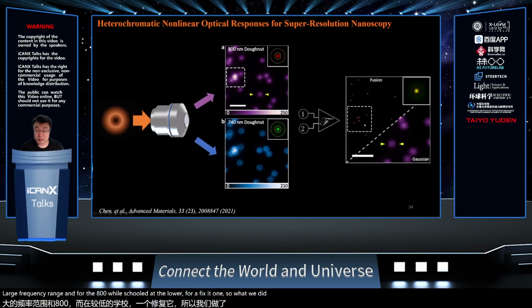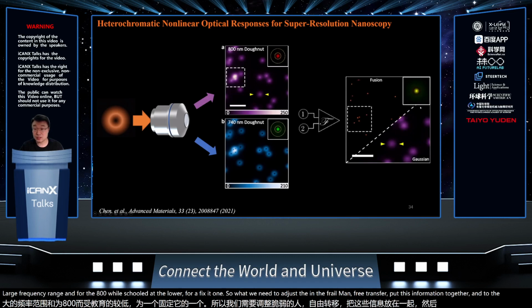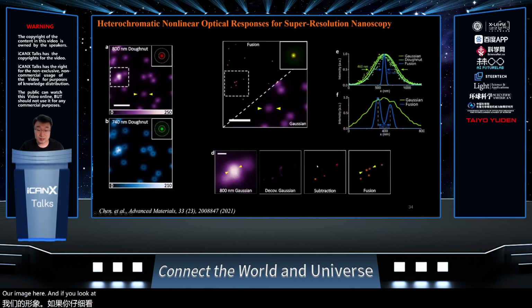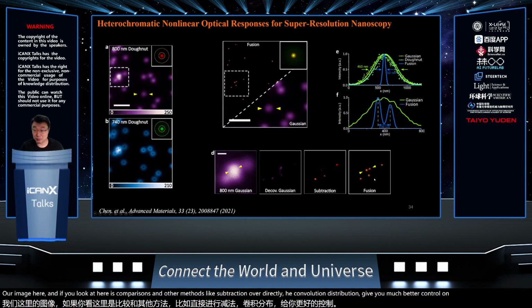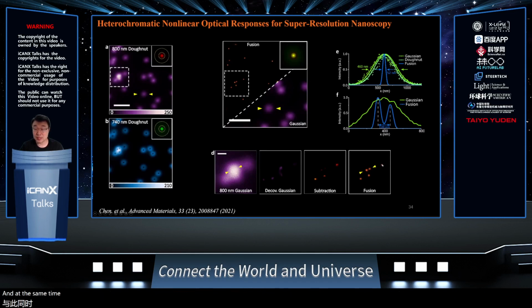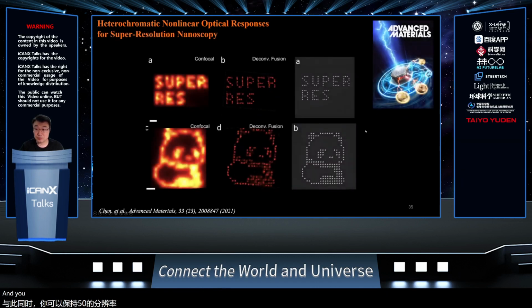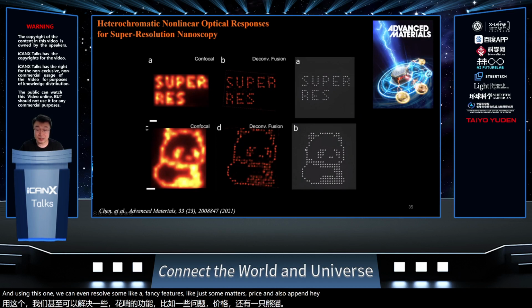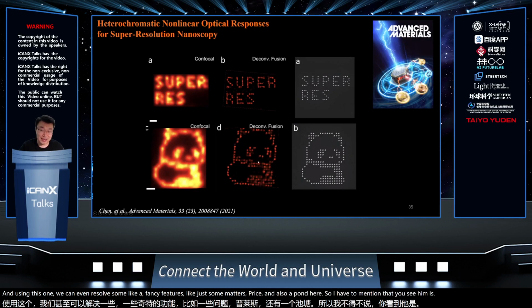What we did is, in the Fourier domain, put this information together and do the Fourier transform again, and then you have a much better image. If you compare with other methods like subtraction or direct deconvolution, this fusion gives you much better control on the aberration, and at the same time you maintain the good 50 nanometer resolution from this donut beam. Using this, we can even resolve some fancy features, like letters, and also a panda here.